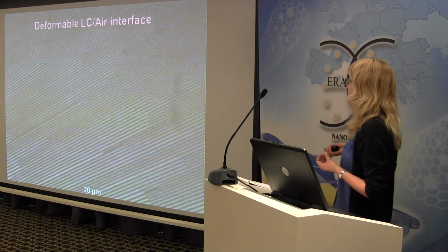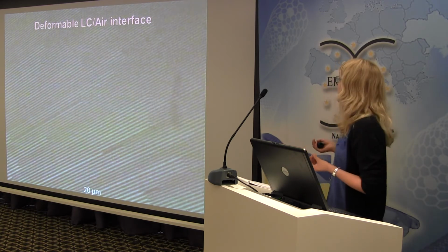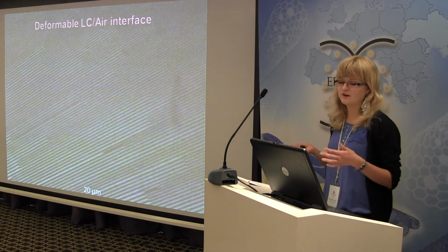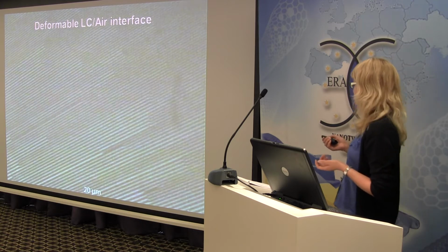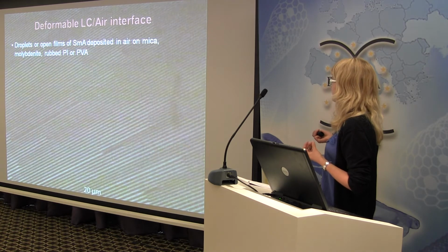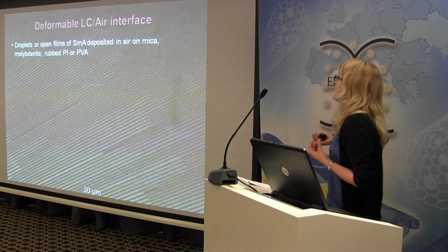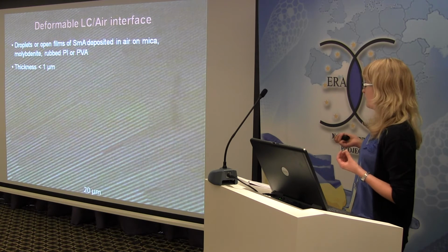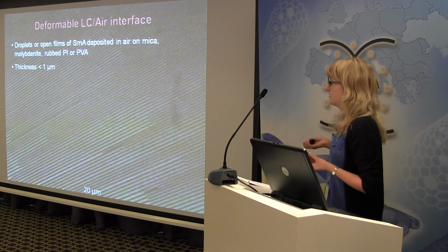As for sample preparations, we've been studying two different types of structures. Deformable interface, where it was open droplets or open films of liquid crystal deposited on air. And we checked different types of liquid crystals and different surfaces, of course. So the liquid crystal droplets were deposited on air in the isotropic phase and then cooled down to the smectic phase.